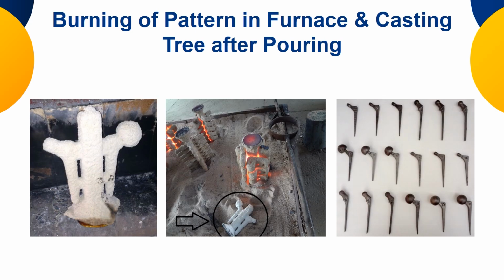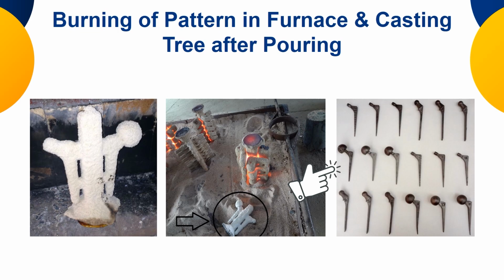Here one of the negative parts or disadvantages is removing the polymer, which was ABS in this case. I have to raise the temperature above 1050, whereas if I use wax, this will be maximum up to 182 or 200 degrees Celsius, right? So after the cavity is created, then putting in stainless steel 316L or stainless steel 304 as per the requirement, these benchmarks have been prepared. So a typical commercial application for developing these types of hip joints in-house is very much possible in our lab.